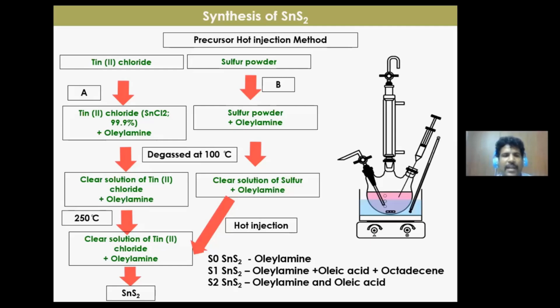In order to avoid those unwanted situations, we degassed this system. After getting a clear solution, the solution B available in flask B is loaded in a syringe and injected into flask A at 250 degrees centigrade. After the tin chloride solution becomes clear and is heated up to 250 degrees centigrade, the solution is ready. After that, the flask B solution is injected. So at 250 degrees centigrade, the material is formed. This is the idea we have used to synthesize tin disulfide. In this, we have chosen different solvent combinations. The first, S0, SnS2, is synthesized with only oleylamine. So S0 represents oleylamine. Both flasks were filled with oleylamine.